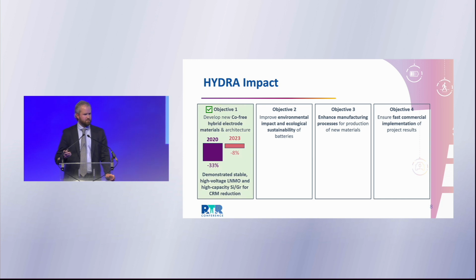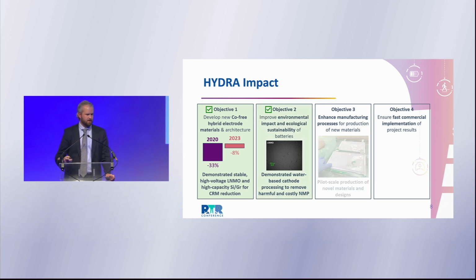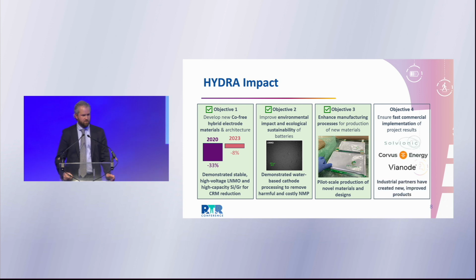Objective 2, did we improve the environmental impact and ecological sustainability? We did. We demonstrated that you can use water-based cathode processing and remove the presence of harmful and costly NMP from that process. Did we enhance manufacturing processes? We've showed that it's possible to do these kinds of things not only on coin cell, not only on single layer pouch cells, but also on relatively large scale multi-layer pouch cells that are relevant for industrial applications. And finally, did we ensure the fast commercial implementation of the results?